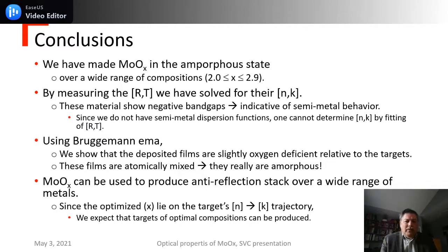One thing that is really important to understand is that because the effective medium approximations work so well, these materials truly are atomically mixed, as we should expect. And finally, because these N and K fall on the trajectory that I mentioned, we can expect that these samples can be made by targets of specific composition.